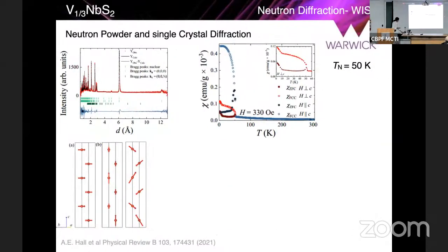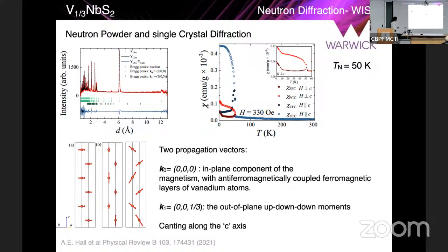Now, the next TMDC we looked at was the vanadium third. And here we did both neutron powder and single crystal diffraction using the WISH instrument at the ISIS spallation source in the UK. And we were able to establish, through solving both the powder as well as the single crystal data, the actual magnetic structure that we think is the ground state of the vanadium third.